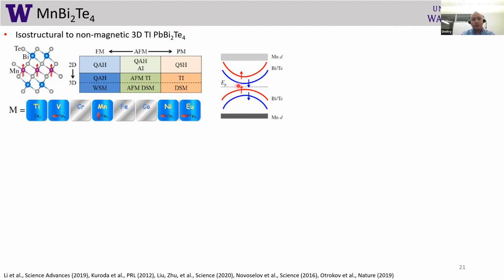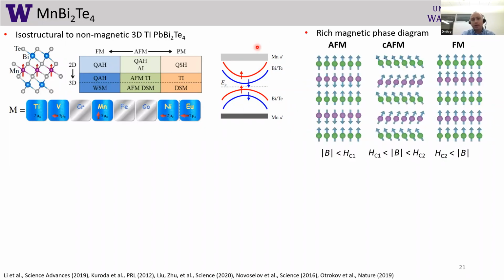And the beauty of this is that essentially all band structure comes from bismuth and tellurium orbitals at low energies, meaning that the physics is more or less the same, but manganese bands, which are far away, spin split the bands and introduce a magnetic state in the system. Another interesting aspect which distinguishes it from traditional magnetic TIs is the fact that it has a rich magnetic phase diagram, meaning that there are 3 different states, which I'll talk more about.